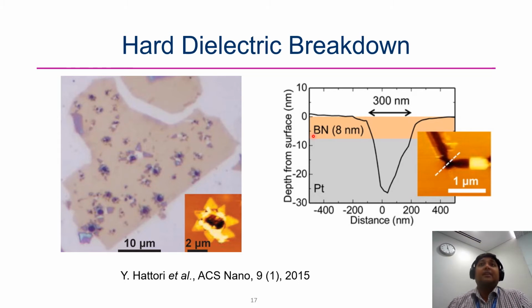So other than the noise spectroscopy, it's very important to look at and understand the dielectric breakdown in hexagonal boron nitride before it can be used for 2D materials. Some of the work has looked at the hard dielectric breakdown. When I say hard dielectric breakdown, it means the current compliance is much higher, typically more than 10 microamps to milliamps range. In this experiment they have a metal substrate, an hBN single crystal, and they went with the AFM, applied some electrical stress, and after that they were trying to image. This is an optical micrograph and this is the AFM picture.